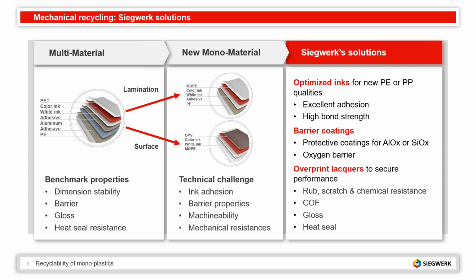In Siegwerk, we are working on this challenge since quite a while, and we already have developed a couple of solutions that enable this transformation. One challenge that you have is when you change the web you're printing on, you will have different requirement regarding adhesion and bond strength for this new web. And this we have tackled some time ago. So we have inks that are optimized for that and that work on these new monomaterial films and give you an excellent adhesion and bond strength.